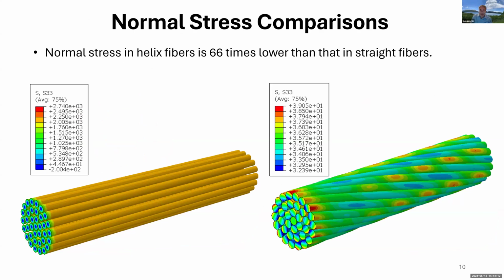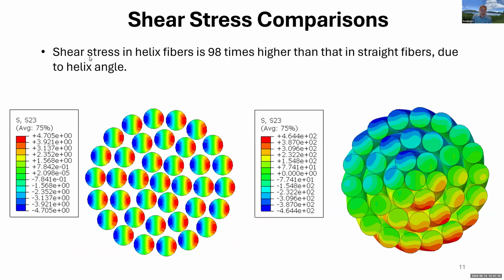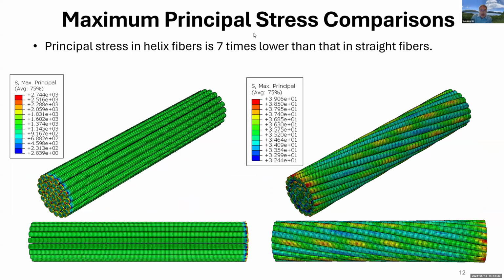The stress is smaller. And if you compare the shear stress, of course, the helical fiber bundles will have a much, much higher shear stress, 98 times higher than the straight fibers, which is understandable. And if you compare the maximum principal stress, again, the helical fiber is 7 times lower than the straight fibers. Again, this is a good sign for using this new configuration.